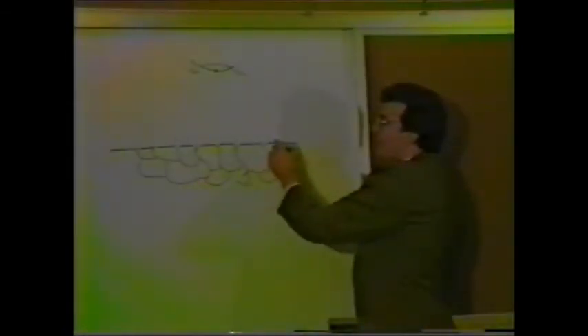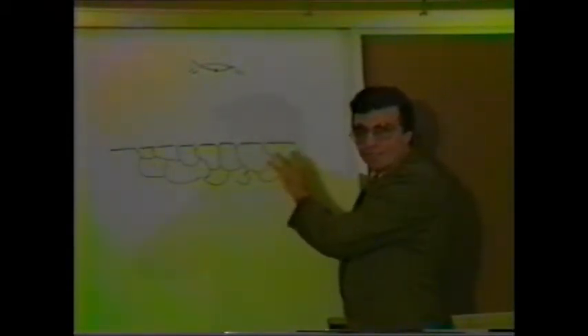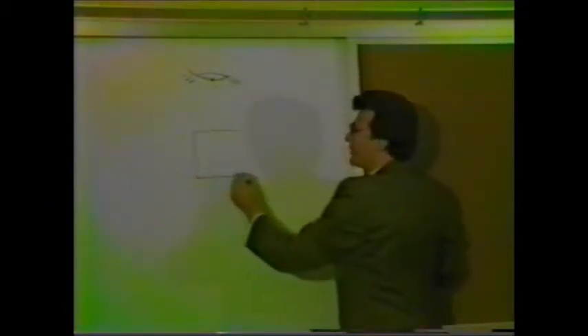And what you do is, as you're looking at these grains, you want to get an idea of, again, relative size of these. Now, the American Society for Testing and Materials, the ASTM, has a formula that will tell us whether the steel is so-called fine-grained or if it is coarse-grained. Now, to tell whether steel is fine-grained or coarse-grained, we scan the steel at 100x magnification, and we want to count the number of grains that would intersect a 1 square inch area. This I'm going to call 1 square inch. A 1 square inch area viewed at 100x magnification.